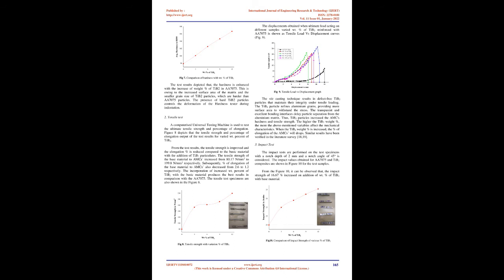The microstructure of the composites showed that TiB2 particles are scattered equally and uniform particles exist in the metal matrix. This indicates that the stir casting process used for manufacturing the specimens is satisfactory. Furthermore, the microstructure of AA7075/TiB2 made by stir casting indicated a strong bond between the matrix alloy and the reinforcement particles.